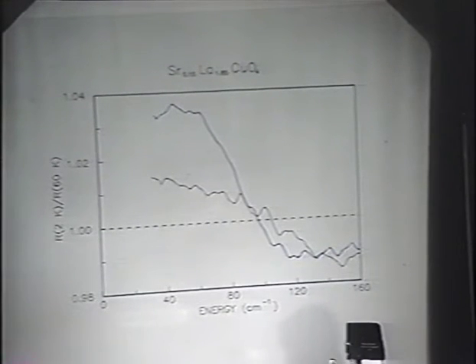These are two different samples we've measured, and the interesting thing to note here is that we get a somewhat smaller gap for materials that show a larger fraction of superconductor. Now, this is perhaps linking up with some of the other far infrared work where they see a considerably smaller gap even than this, and a much higher percentage of the superconducting effect.